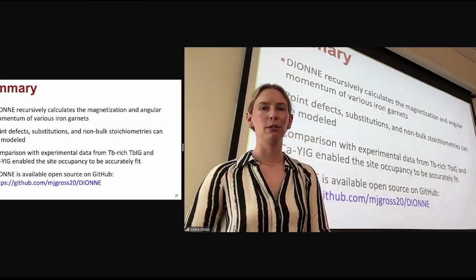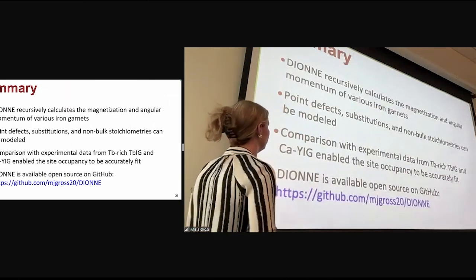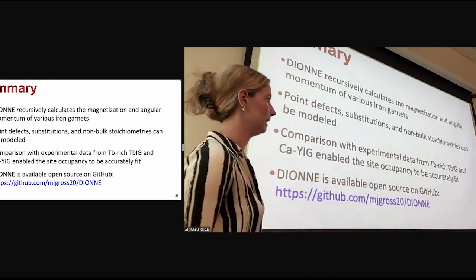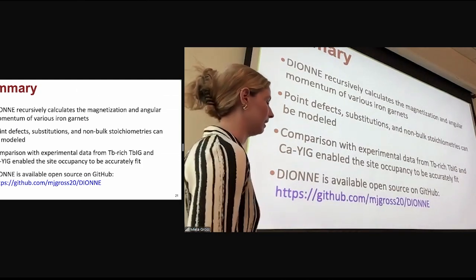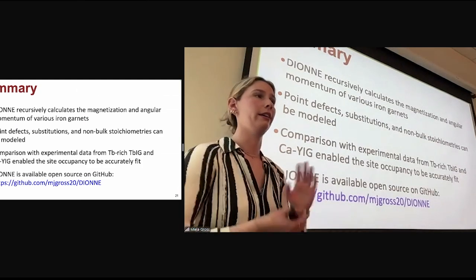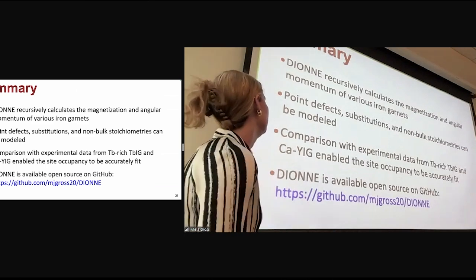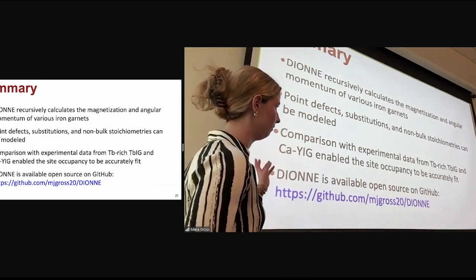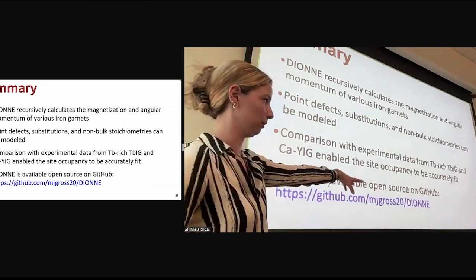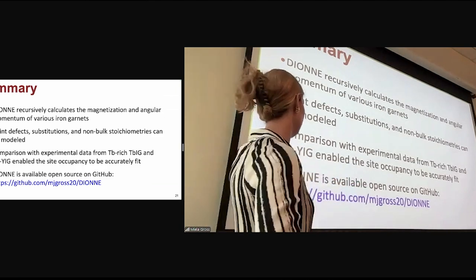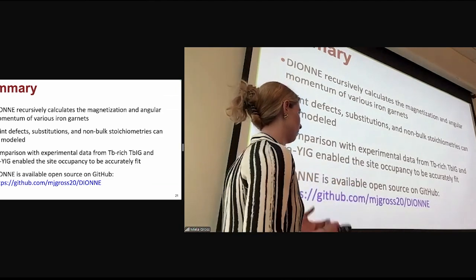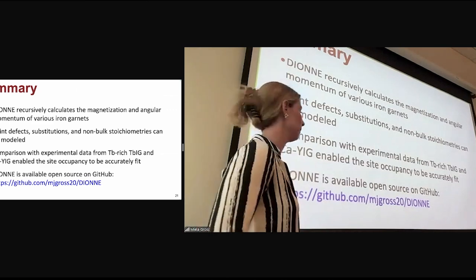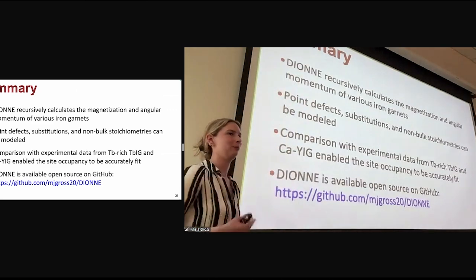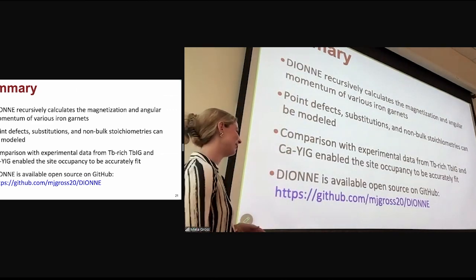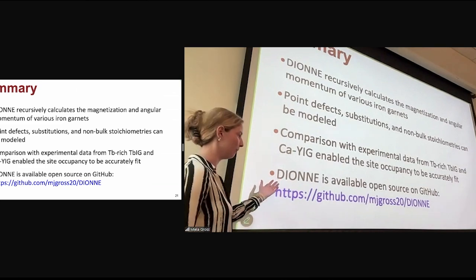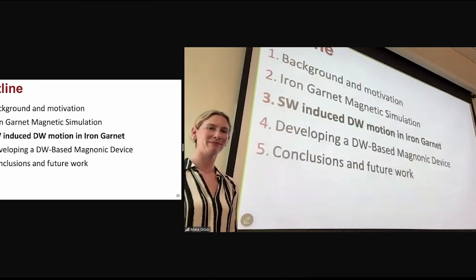So in summary, we've shown that our model, DIONNE, recursively calculates the magnetization and angular momentum of various iron garnets with a lot of defects and off stoichiometries. And we can use this model to fit experimental data like the terbium-rich terbium iron garnet and the calcium YIG, which allowed us to determine more precisely the site occupancy of those samples. And I wanted this model to be available for not just me. So I put it on GitHub and it's available open source at the following link here.